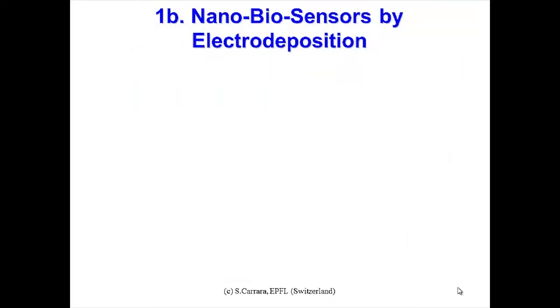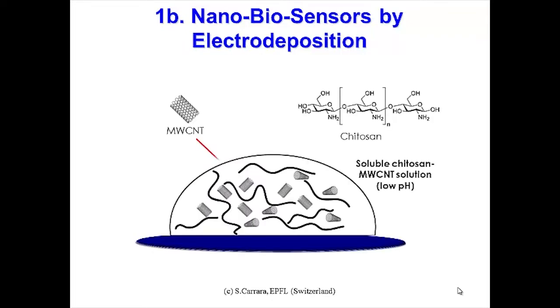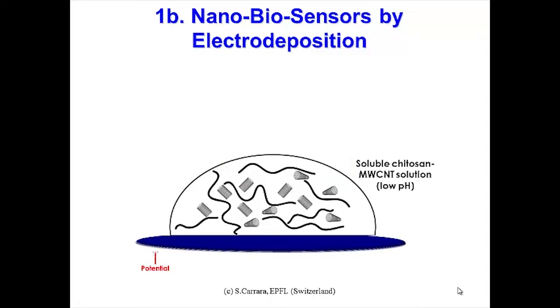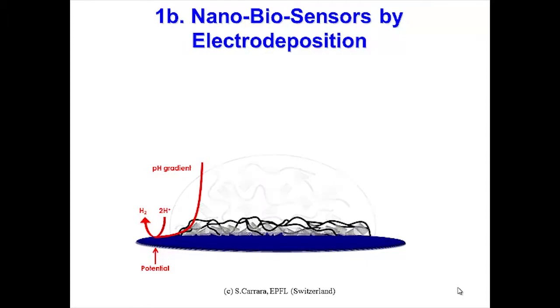We also tried in the lab another approach, the electrodeposition of carbon nanotubes. Even in this case, we need to cope with water-soluble mixtures. So we get a mixture by using multi-walled carbon nanotubes and another water-soluble polymer, the chitosan. Then, by applying a potential to our working electrode, we can establish a variation of pH, a gradient of pH that forces the chitosan to condense on the electrode, and in doing that, the chitosan traps all our carbon nanotubes. Also in this case, the final result is carbon nanotubes transferred onto our microfabricated electrodes.